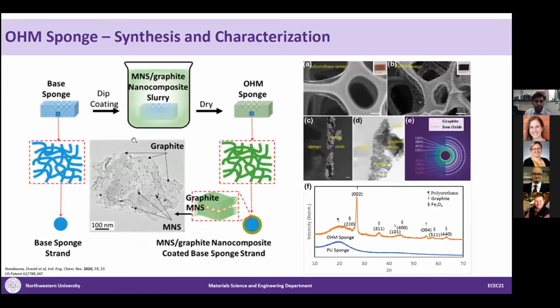So the way we make the sponge is we just take any base sponge. The sponge could be polyurethane, cellulose, melamine, or any other porous material, and then we dip coat it in a nanocomposite slurry, which is made of graphitic carbon and iron-based nanostructures. And that's how the OHM Sponge is formed. So on a simple strand of a basic polyurethane sponge, there is a very thin coating of a nanocomposite, which looks like this.